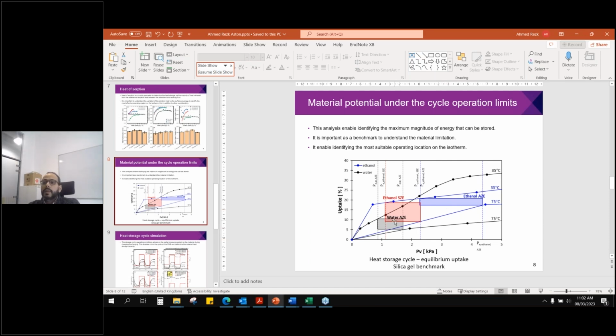Here actually water is something in between, but when we look at the heat absorption for water in this case study, we found that the heat absorption of water was higher than ethanol. So we can find a conclusion from this figure that, yeah, I can go to this cycle, the red cycle, or the black cycle, but it is not feasible enough actually to look at this blue cycle. You can find actually, we'll try to link between the material properties and the application part of the research, is not only the material characteristics.